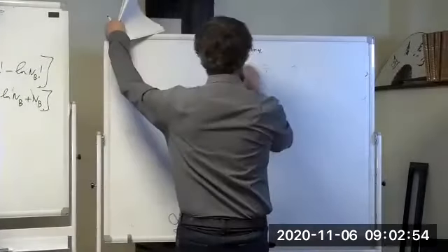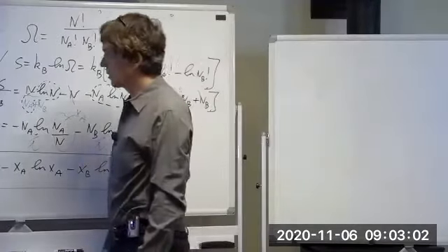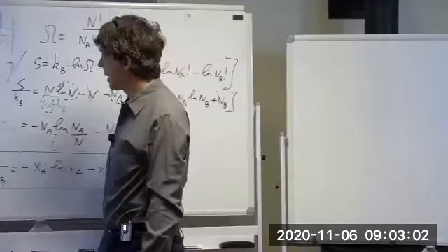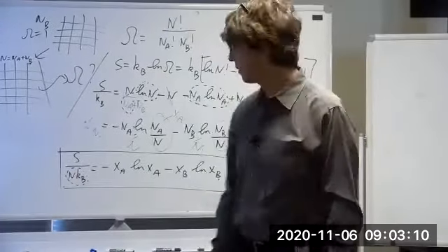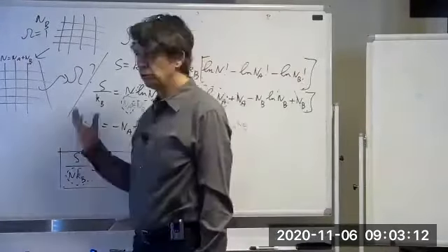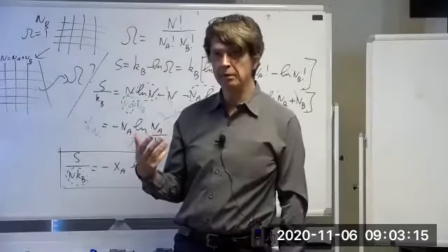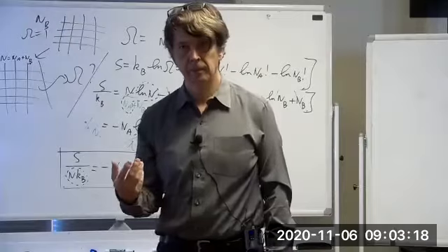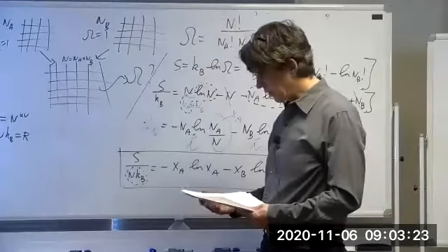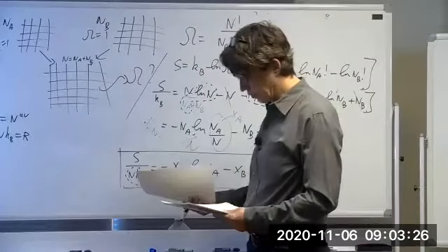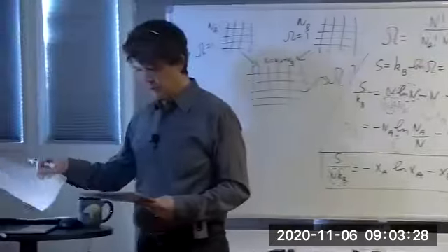This is a derivation that you should do a few times in your life because it's a sort of classic. It shows up many times in other parts of materials science as well, when people ask for the entropy of distributions on lattices. For example, exactly the same math is used to calculate what the equilibrium vacancy concentration is in materials. You calculate the possible distributions of vacancies, and you can show from that that vacancies are equilibrium defects, unlike one-dimensional and two-dimensional defects.